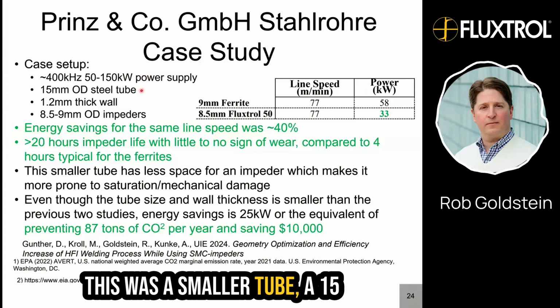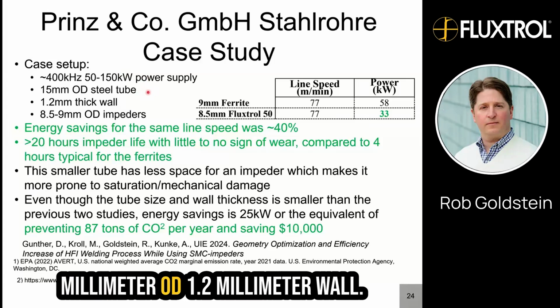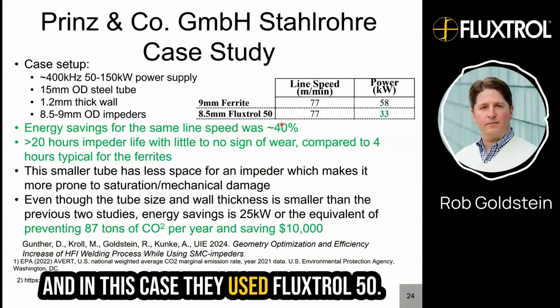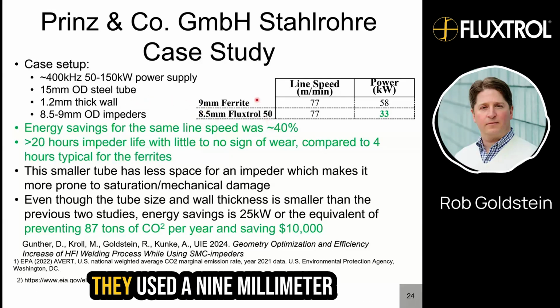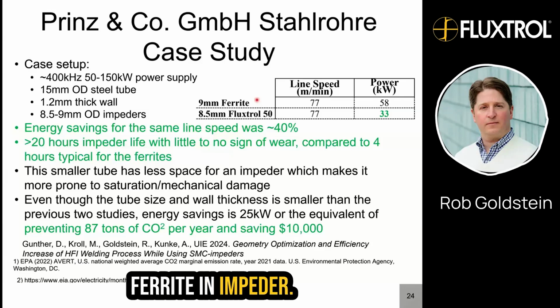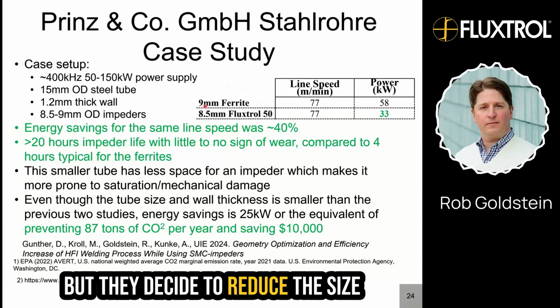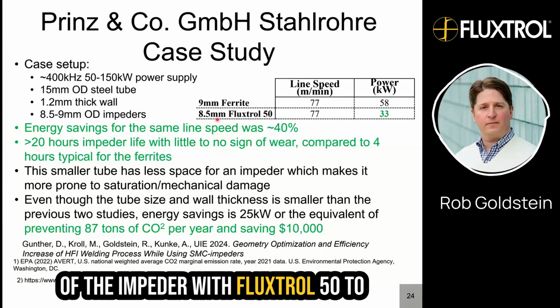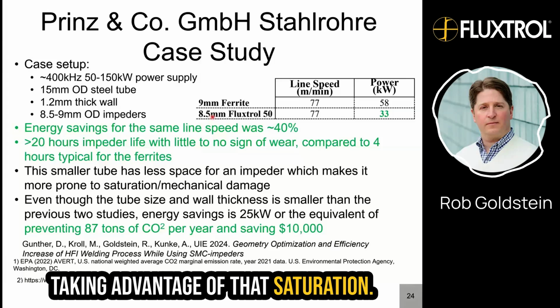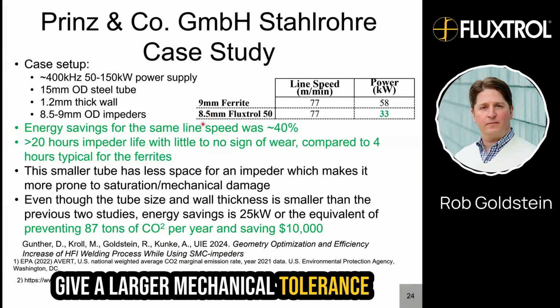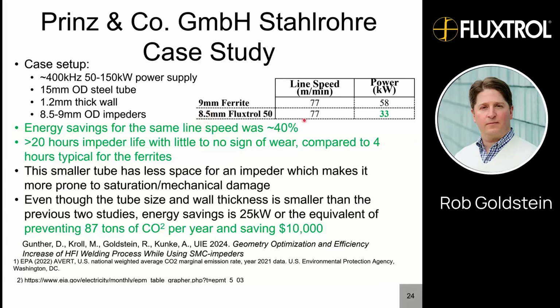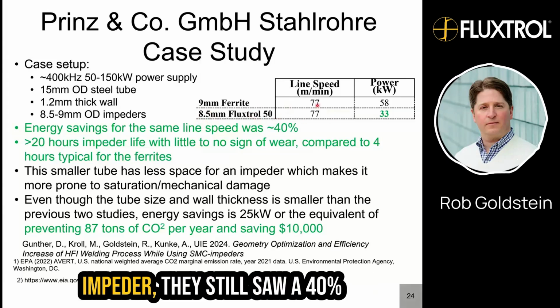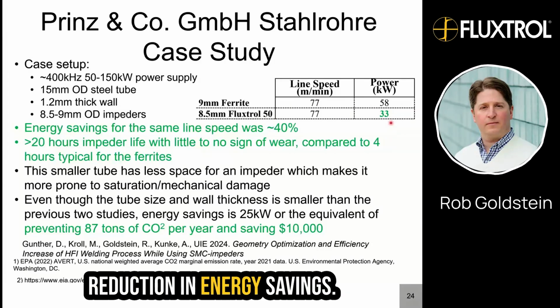This was a smaller tube, a 15 millimeter OD, a 1.2 millimeter wall. And in this case, they used Fluxtrol 50. They used a 9 millimeter ferrite impeder, but they decided to reduce the size of the impeder with Fluxtrol 50 to take advantage of that saturation and give a larger mechanical tolerance to 8.5 millimeters. Even though they used a smaller impeder, they still saw a 40% reduction in energy savings.